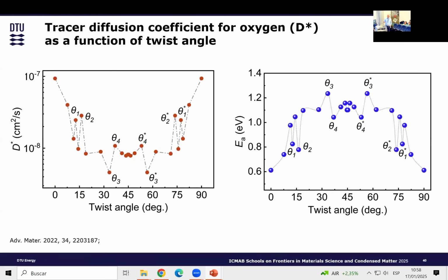We did some calculation and work earlier. We looked at the trace diffusion coefficient of oxygen as a function of twist angle. The idea here is you take 2 strontium titanate layers and rotate them to different degrees. We looked at how easy or how difficult it is for oxygen to move from one side to the other side. Basically, it's the trace diffusion coefficient of oxygen. And we found out that there is an angle dependence here. Unfortunately, it is going the opposite way, so it becomes worse when you twist it.